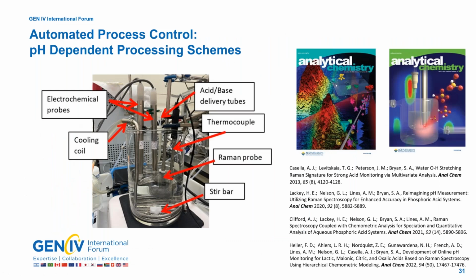We can use this pH measurement in a demonstration for automated pH control. In this case, I'm showing a large beaker that is really our feed container, where we have a citric acid, weak acid solvent, which is used in a Talspeak separation campaign. And it's a weak acid, just like phosphoric acid is a weak acid. We can use that as a pH indicator as well, and we've built chemometric models for that, so we can measure pH based on the Raman spectrum of that.